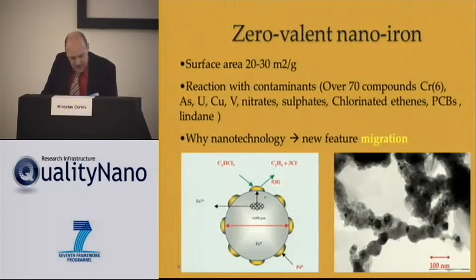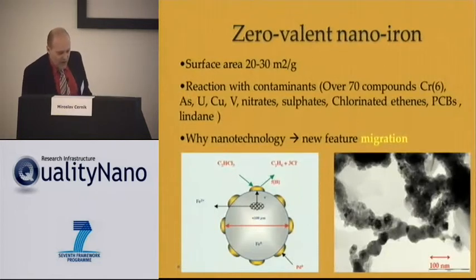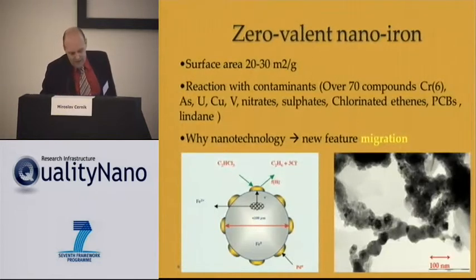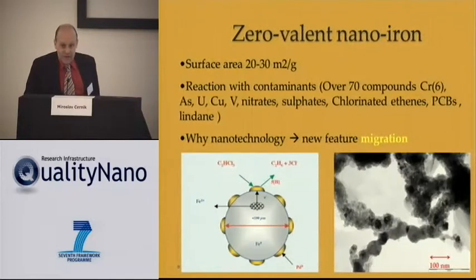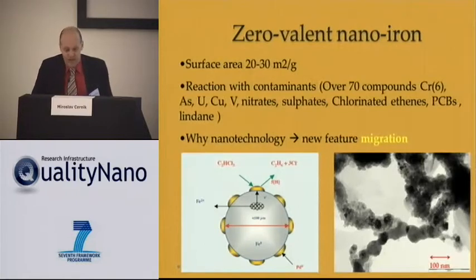One of the possibilities is to use iron nanoparticles, which have a size of about 80 nanometers. They have a surface area exceeding 20 square meters per gram, and you can find in the literature that they work with many potential contaminants like chromium-6, arsenic, uranium, nitrate, sulfates, chlorinated ethenes, which are the most widespread pollutants, PCBs, lindane, for example.